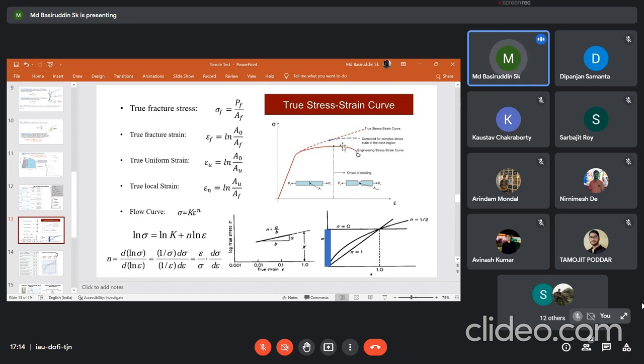Now, in general, if we have this sort of stress-strain curve, we can regenerate this curve by following the flow curve equation, that is sigma equals K epsilon to the power n. How can we get this equation? If you have the discretized data, then plot the stress on the y-axis and the strain on the x-axis, and derive an equation using Excel or Origin. You will find this equation, which is known as the simple power law equation. But of course, this is not the exact solution. If you just follow these equations without doing a test, you cannot regenerate the exact curve, but quite approximately you can redraw this sort of curve without doing any experiment.